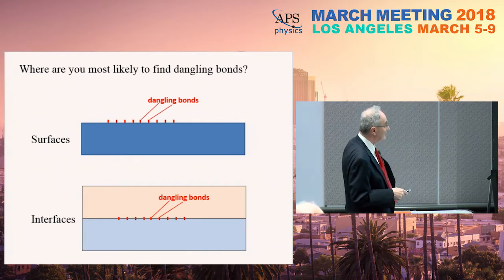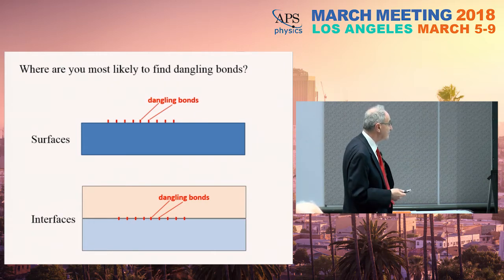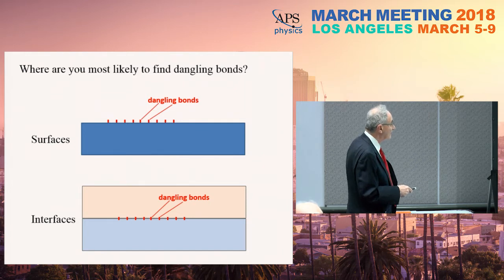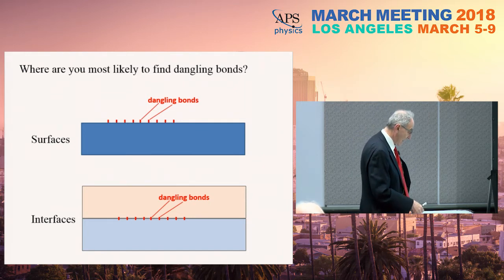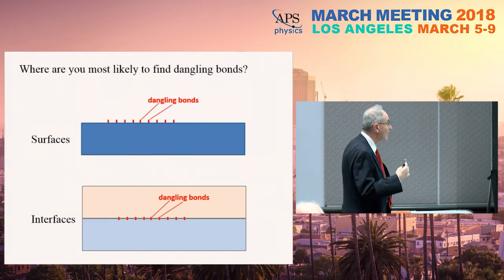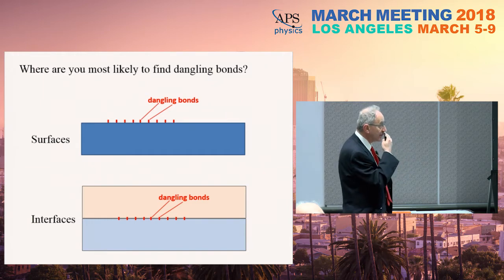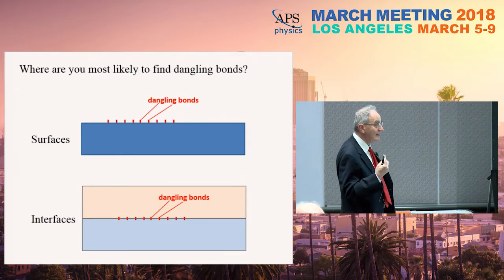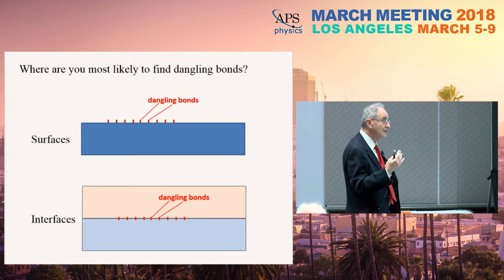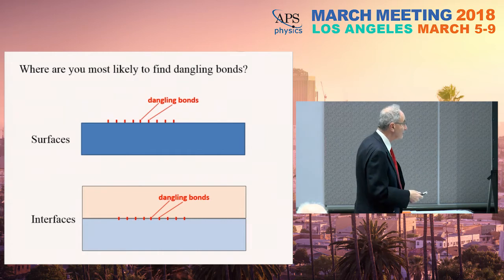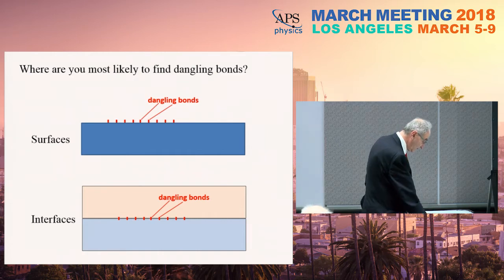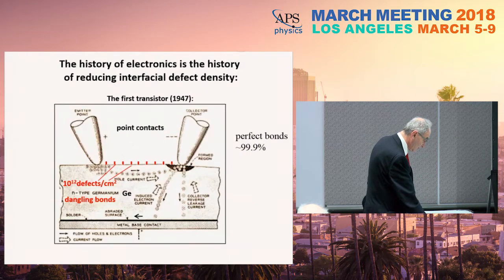If you're doing this at an interface, it's the same story. If you have an interface between two rather different materials, they won't necessarily line up, and you'll be left with lots of dangling bonds at the interface. Think of the dangling bonds as being an impurity. Even if you have very high bulk purity, it doesn't mean anything — it has to be chemically and structurally perfect, with no internal dangling bonds either. But it's the surfaces that are the most severe problem.